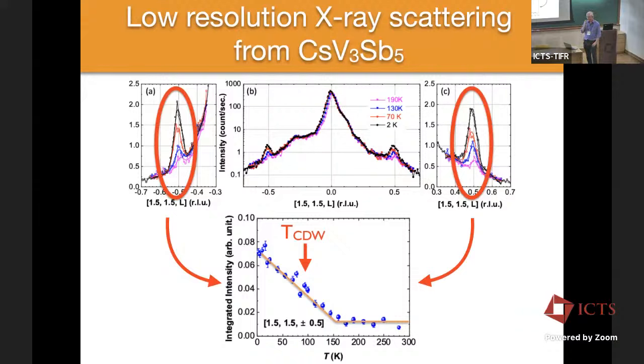Yeah. And the second question was that with the low resolution, you also have a larger spot size you're dealing with, and low energy, and there's less local heating, right? Right. Compared to the... Yeah. So how do I connect that to why the high resolution wouldn't be able to see any fluctuation regime? In principle, they can. And in fact, Stephen Wilson showed some results. It was not in this system, it was in the other one that had those trimers. I don't know if you remember exactly what he was saying, but they were seeing diffuse scattering. And so in principle, you can.